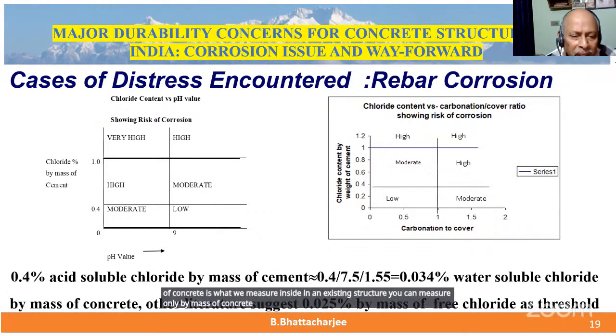Otherwise, there is a lot of error. Although a lot of people are reporting it in terms of cement or per meter cube, with IS 456-2000. Actually, the IS 456-2000 restriction has come from the BS code, or BS-EN now, but it has come actually from the BS code. That was meant for fresh concrete, new concrete. Now, in new concrete, for every individual component, you know what the total chloride is.